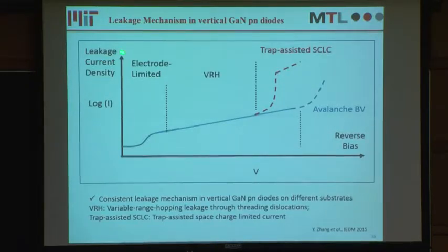So if we look at the leakage current density as a function of the reverse bias, typically at low reverse bias, this leakage current might be limited by the electrode or the surface. Then the leakage current will mainly be determined by this variable range hopping through the dislocations in the drift region.